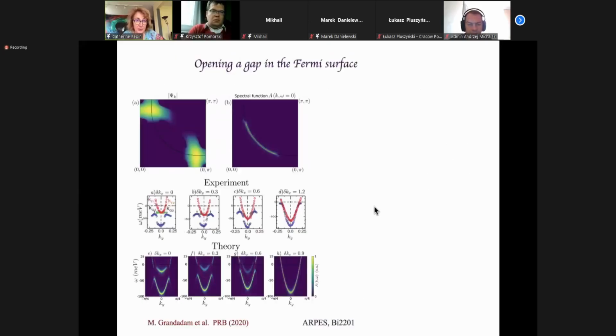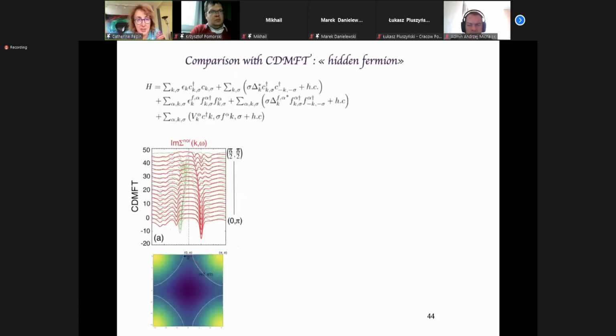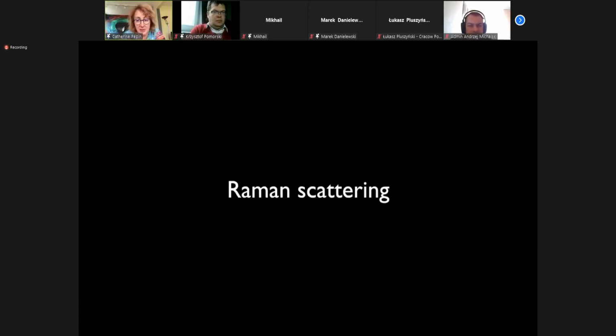And one of the good things we could get, it's an indirect experiment, is the opening of the pseudo gap formation in bismuth 2201. And we got some very nice fitting with the data, with the backbending of the pseudo gap forming not at KF, a bit away from KF, but the band is bending back like that. So there is a kind of Q square scaling, at least in this compound, in the formation of the pseudo gap. We also checked in the spectral function that our constraint was opening the gap. And this fitting with experiment is pretty good. So this I pass, it's a link with the CDMFT.